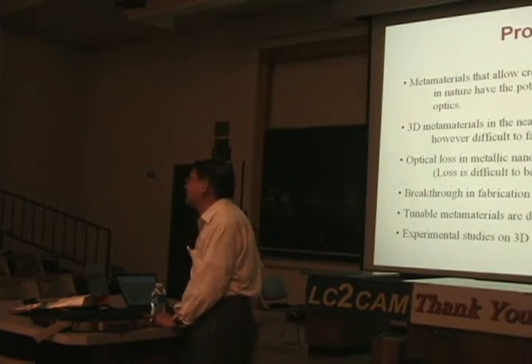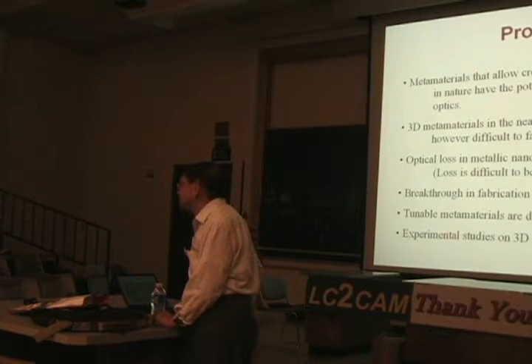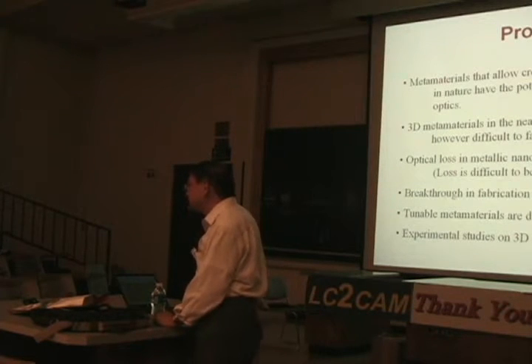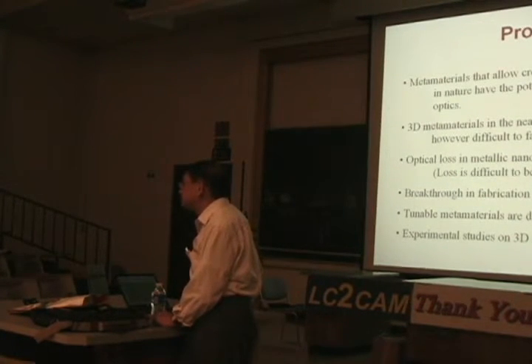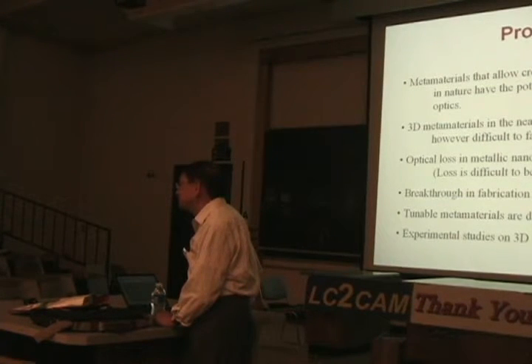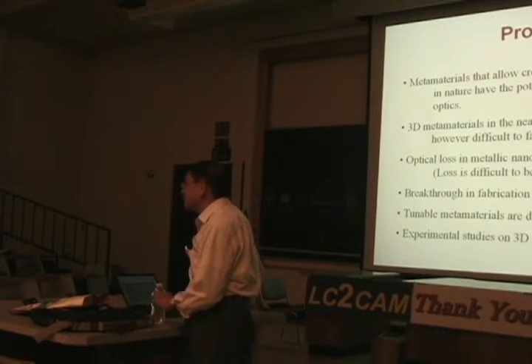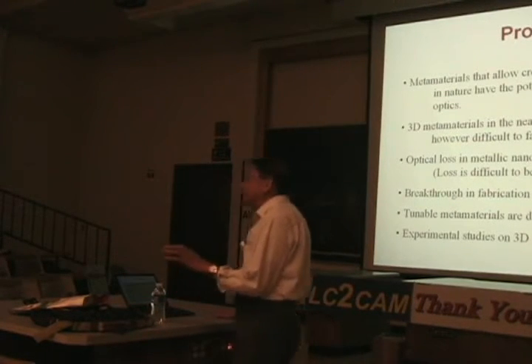So in all of these materials, because of the need to have a higher density of units, you are on a lattice of some kind that you showed as a rectangular lattice. And when you got to the point where you're explaining this resonance narrowing in the nonlinear case, I was expecting to see some influence of the local field caused by the induced fields or the combined effect of the surrounding lattice, such that you had some kind of Lorentz factor due to that. But you seem to be explaining it more with the higher order local field that didn't involve the lattice somehow. So to what extent is that?